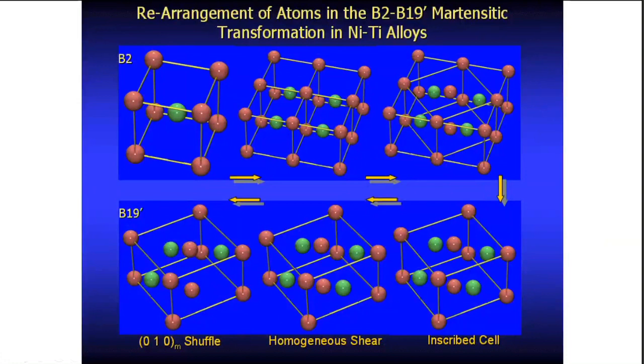You may have a component in which there's only a pure shear, or you can have a component in which you have only the inhomogeneous element that's called shuffle in it. So the martensitic class of transformation is one in which it is dominated by shear. And if you have the three components of it, usually they are dilatation, shear, and shuffle. Now the dilatation means it is something like a hydrostatic change, either an expansion of the lattice or a contraction of the lattice, right? Uniformly in all the three axes will suffer the same extent of strain.